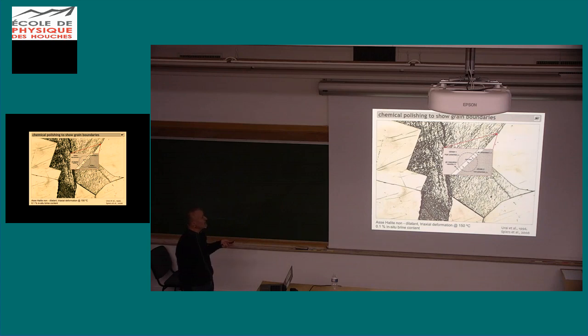And the point is, and we have done quite a lot of observations, we have shown that these grain boundaries contain a fluid film, which is a saturated solution, and it is just 45-50 nanometers thick. But this fluid film increases the mobility of these salt grain boundaries by many, many orders of magnitude, and allows the salt to recrystallize almost at room temperature.